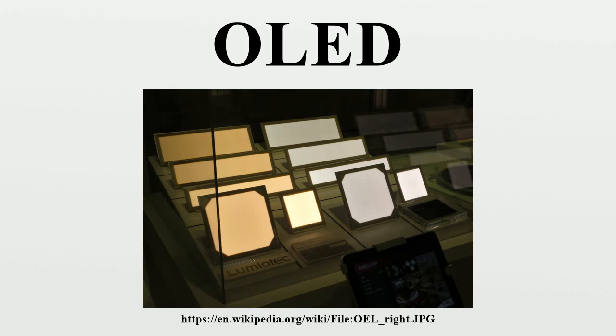Typical polymers used in PLED displays include derivatives of poly(p-phenylene vinylene) and polyfluorene. Substitution of side chains onto the polymer backbone may determine the color of emitted light or the stability and solubility of the polymer for performance and ease of processing. While unsubstituted poly(p-phenylene vinylene) is typically insoluble, a number of PPVs and related poly(p-phenylene vinylene) copolymers that are soluble in organic solvents or water have been prepared via ring opening metathesis polymerization.